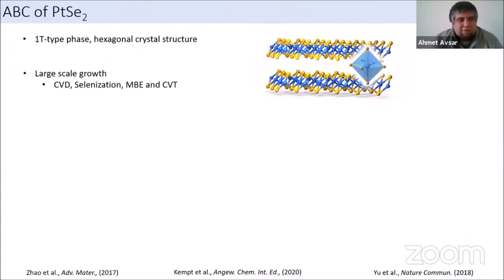Okay, so let me start with the ABC of platinum diselenide. Unlike the other TMDCs, transition metal dichalcogenides, which have the 2H phase, this material has the 1T phase. So whenever someone talks about the monolayer of platinum diselenide, what you need to imagine is a platinum layer, and then there are also top and bottom selenium layers.